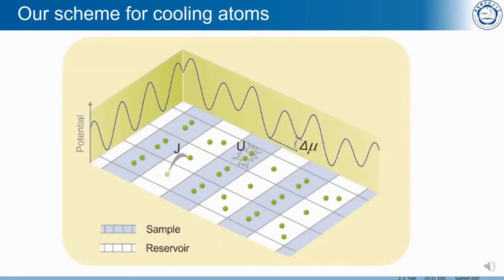This is our experimental realization of the cooling scheme. During the phase transition from superfluid to Mott insulator, while we're ramping up the trapping potentials, we keep a tilt in each double well. So the atoms are grouped into two subsystems. The left rows are the samples, and the right rows are the reservoirs. The samples enter into the regime of Mott insulator earlier than the reservoirs. However, the exchange of particles among the two subsystems transfers entropy from the samples into the reservoirs.